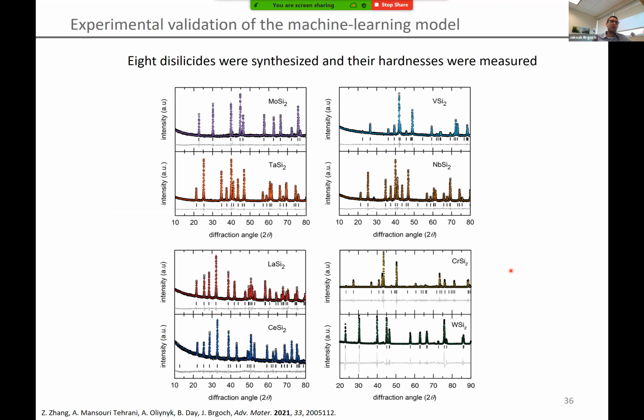In this case, we turned to transition metal disilicides that had never been measured for their experimental hardness. We looked at these compounds because you get a range of crystal chemistries and a whole range of different transition metals that can be used. We were able to synthesize all of these as phase pure products based on their fine X-ray diffractograms.